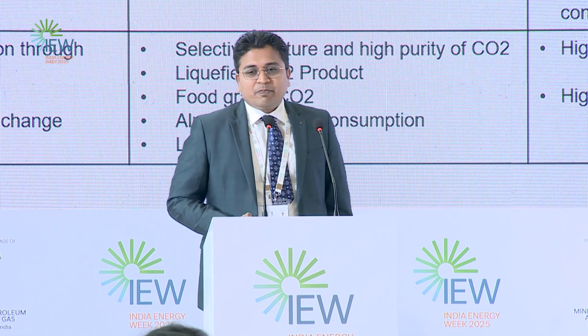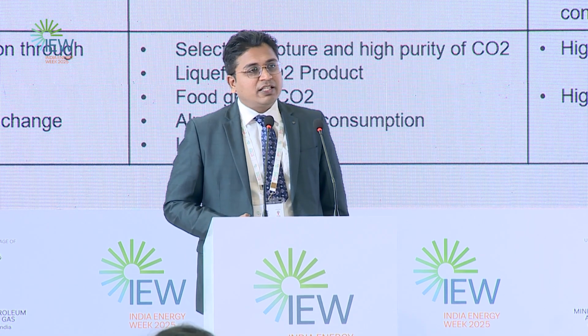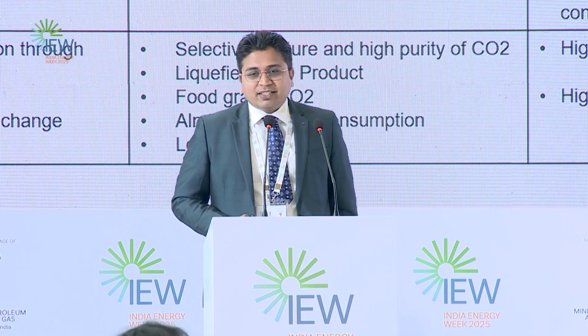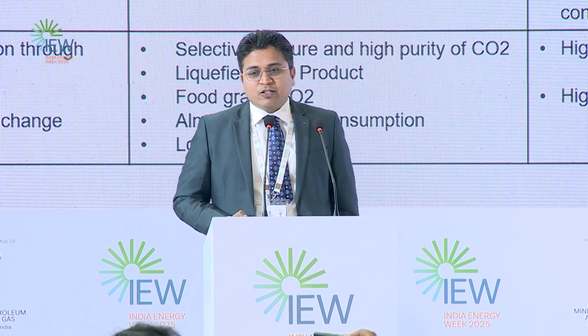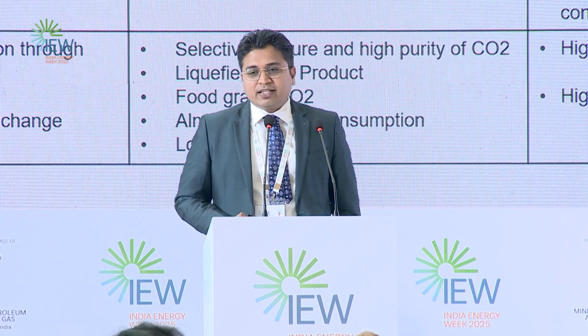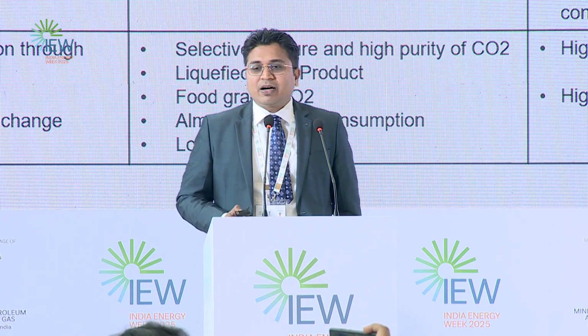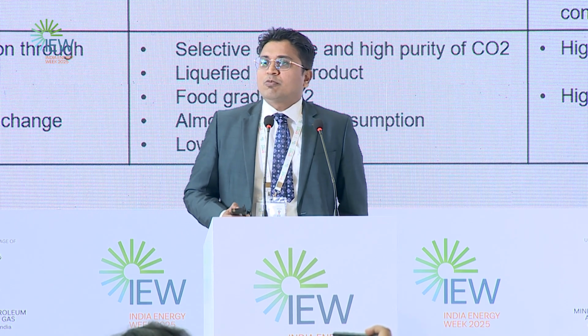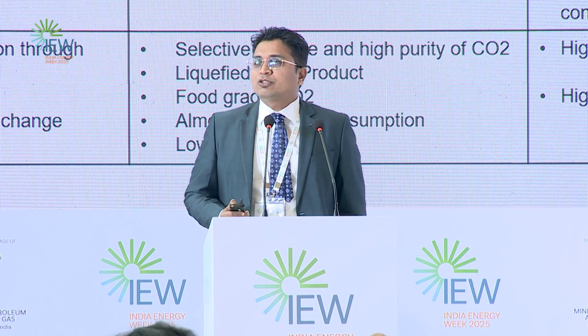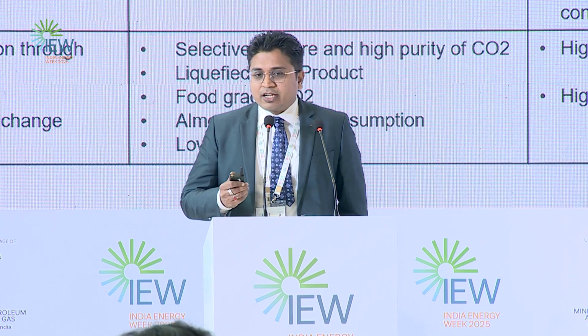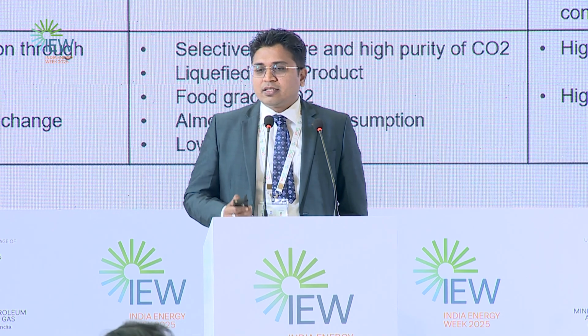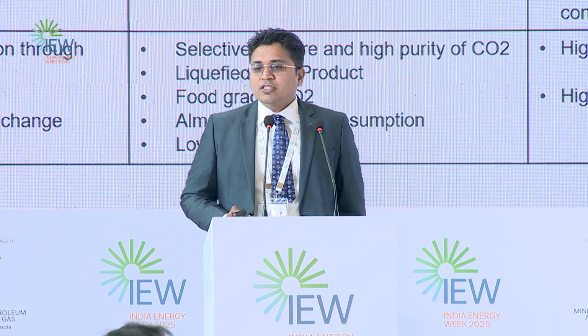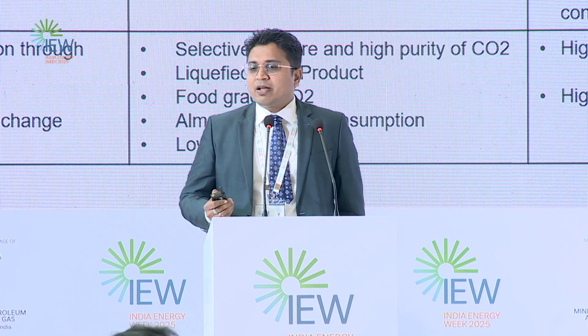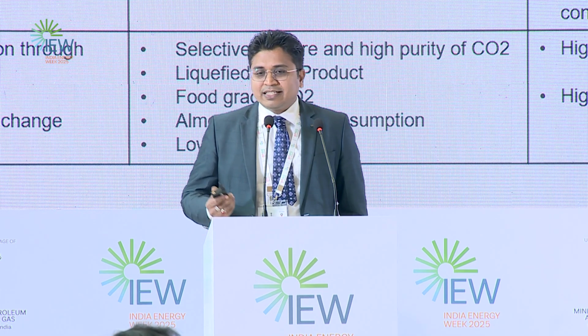So this is the comparative analysis of CO2 capture technologies. As we can see, there is the chemical solvent. The advantage of the chemical solvent is high absorption at low partial pressure of CO2. So if you have a low partial pressure of CO2 in your feed stream, we can go with the chemical solvent. The con, obviously, is the high energy requirement for solvent regeneration.